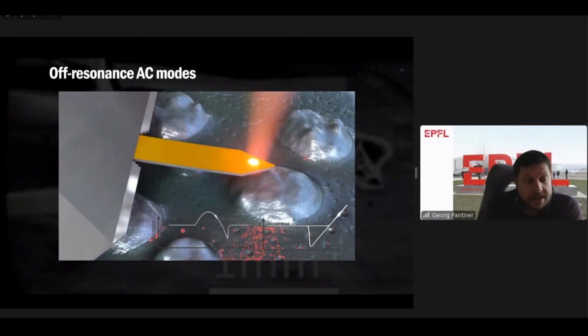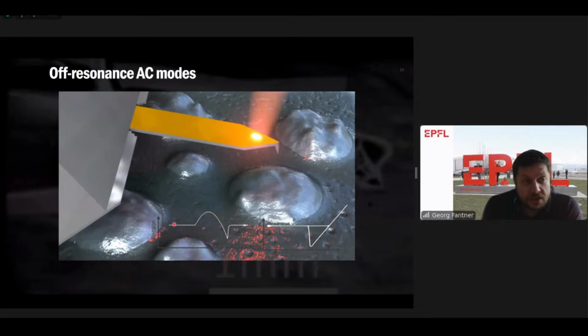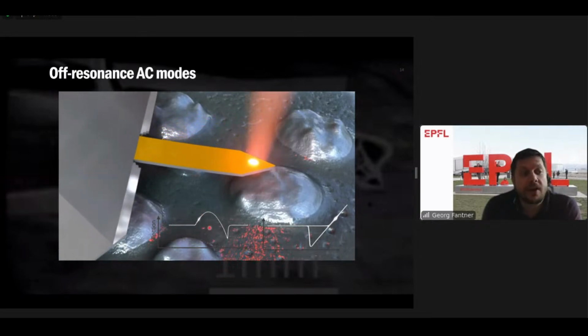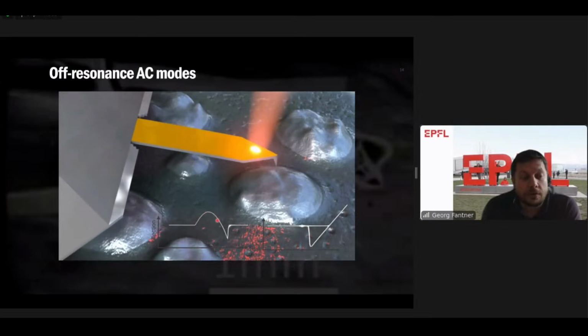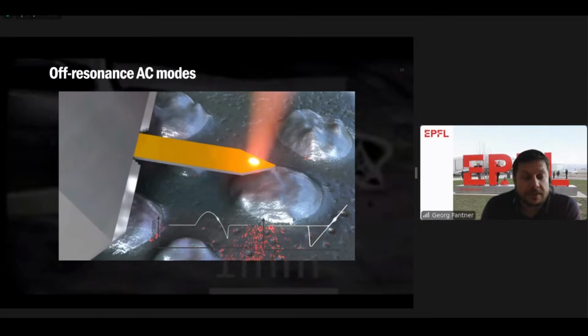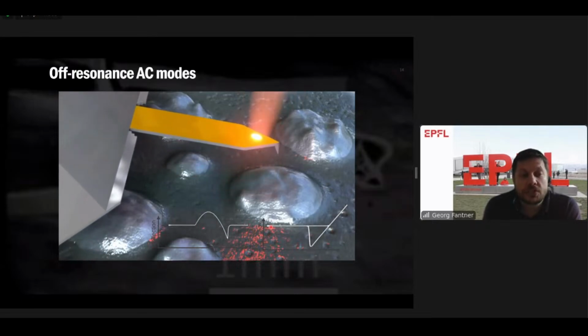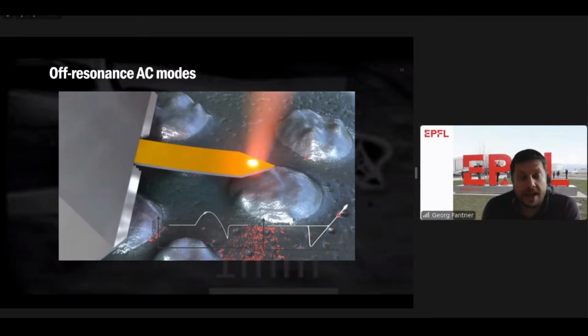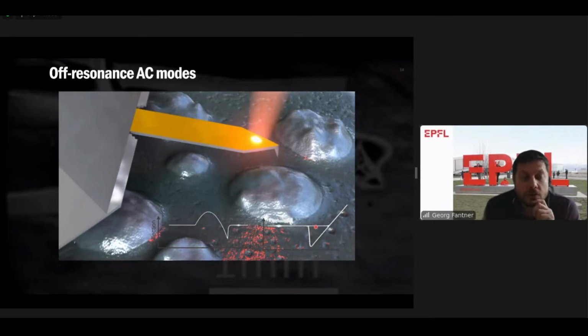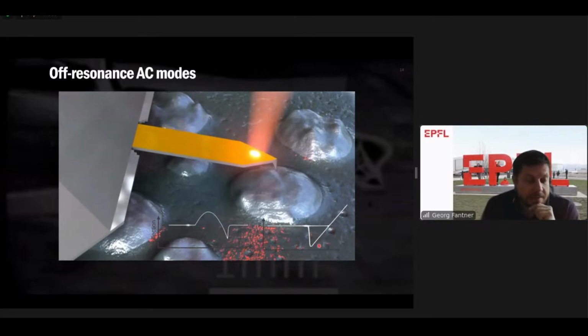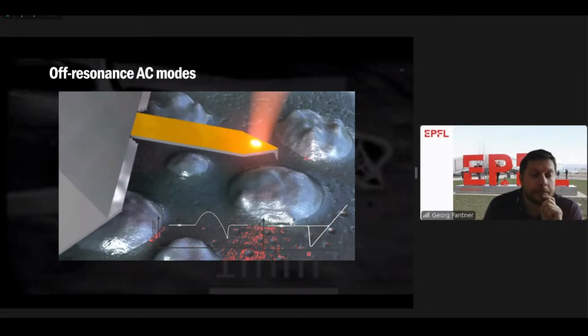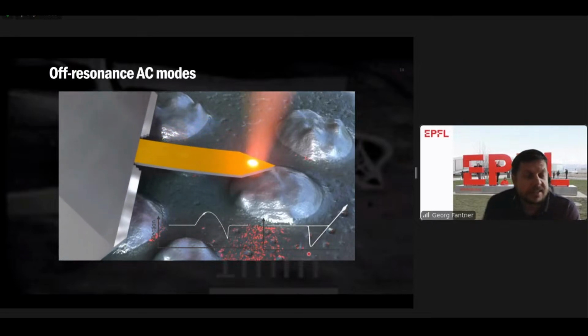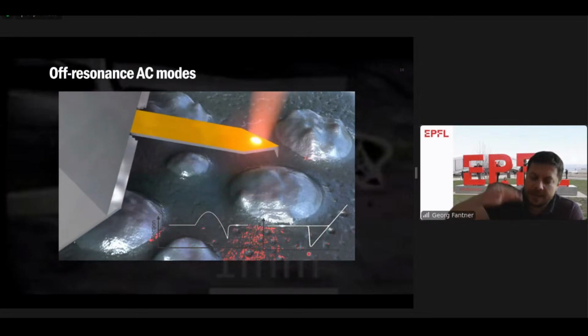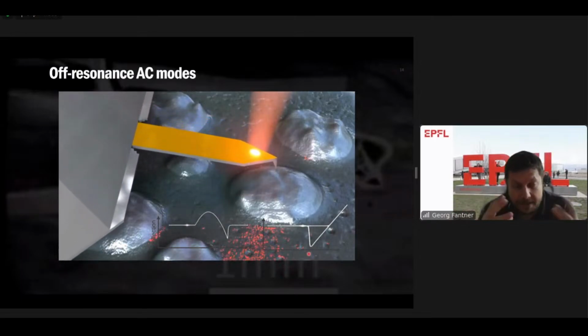The other advantage is that you're not just getting a topography height, but you're actually getting for every pixel such an interaction curve, so the deflection as a function of time. And if we do a little bit of coordinate transformation, we can actually get a force distance curve out of that. So we get a force indentation curve for every pixel of the image. And that is great because we can use it to extract mechanical properties, which we will see a little bit later.